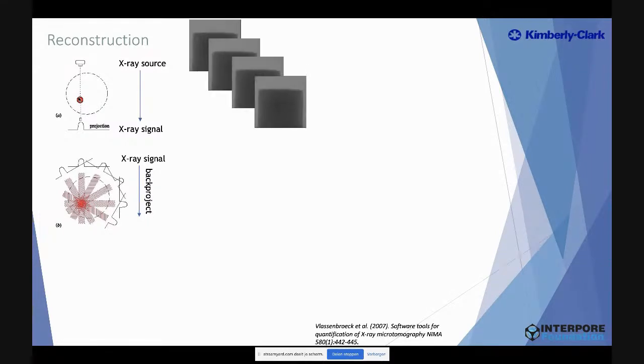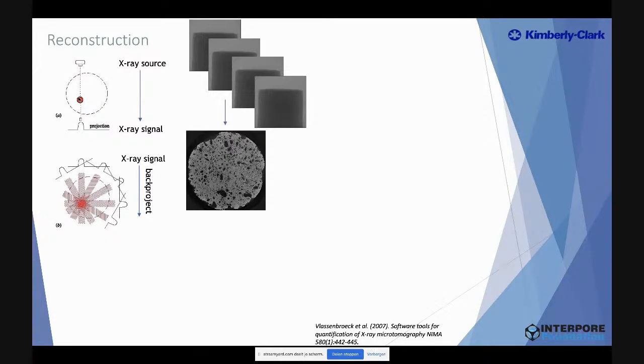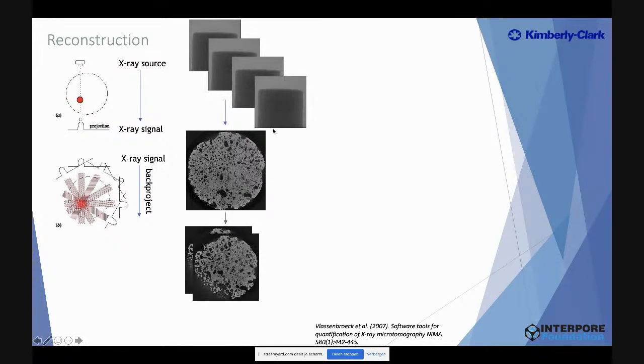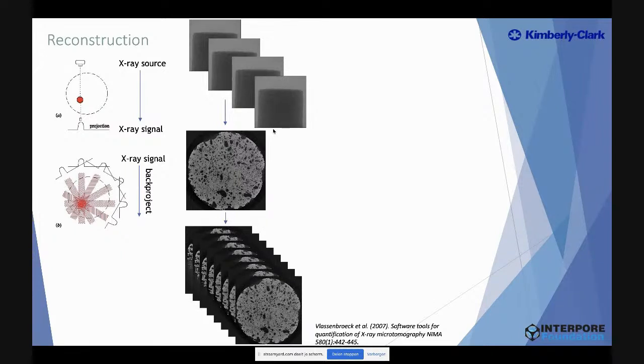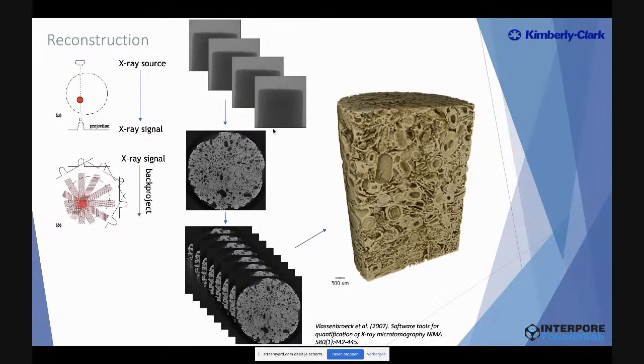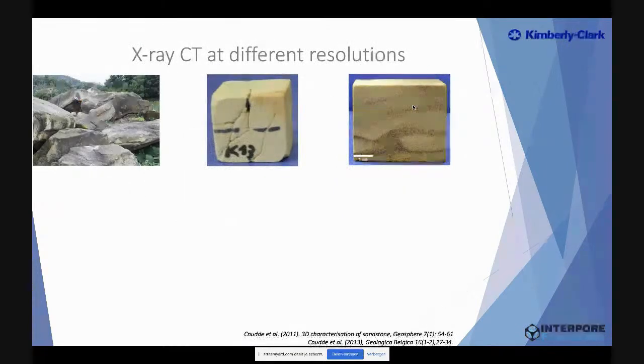So in reality, you take a series of radiographs, then you reconstruct your image, which gives you a 2D reconstruction of your sample. In reality, we have information of your entire volume, so we are able to reconstruct all those slices, and this is then used to render a 3D volume. So like here, a Savonnière, a French limestone, which you can see in 3D in a non-destructive way. So the benefit of using X-rays is that you do not have to do sample preparation, for instance. And so after, if you have this principle, you can start to investigate samples.